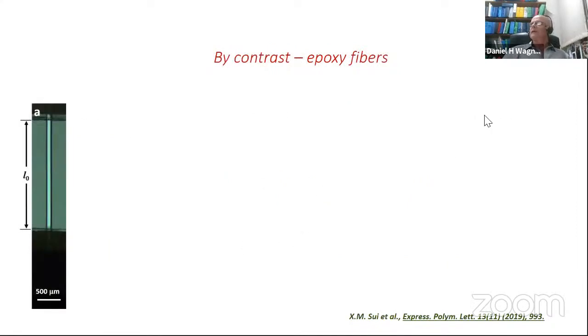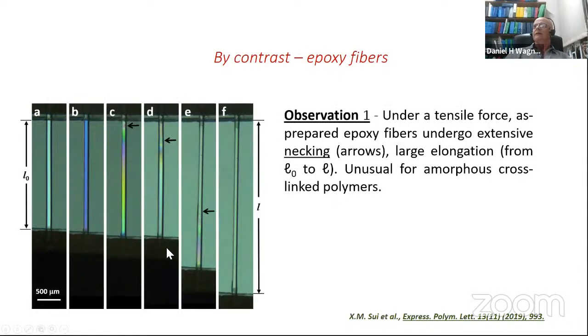Now, if you test the epoxy fibers, things look different. They look like this. Once you increase the stress or the strain on the epoxy fiber, you generate, where the arrow is, necking. This in itself is amazing. I mean, epoxy doesn't neck like a metal or like a thermoplastic material, such as polypropylene, for example. There is no necking usually in epoxy. And so this was a big surprise.